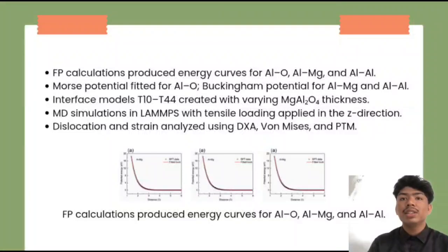In this study, a multi-step computational methodology was applied to investigate the atomic scale strengthening mechanism at the magnesium aluminate-aluminium interface. The process begins with first principle calculations to generate accurate energy-distance curves for the atomic interactions, especially aluminium-oxygen, aluminium-magnesium, and aluminium-aluminium. These curves were essential for understanding how atoms interact across the interface. Next, these curves were used to fit the atomic potential functions for use in molecular dynamics simulations.